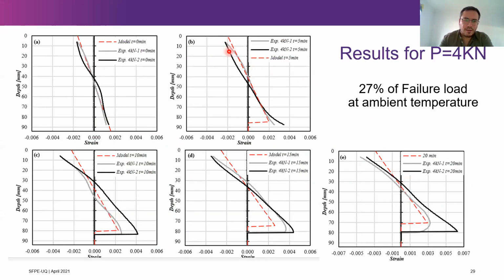But you not only predict the capacity, you can also predict the stress strain profiles. And the continuous lines are the experimental results. These are the results for the 4 kilonewton test. And the red dashed line is the prediction of our model. So the model, because we assume that after 250 you will lose all the strength, that's pretty much showing the progression of the char depth, right? And you see that the results of our model match pretty well the experimental results of the test.